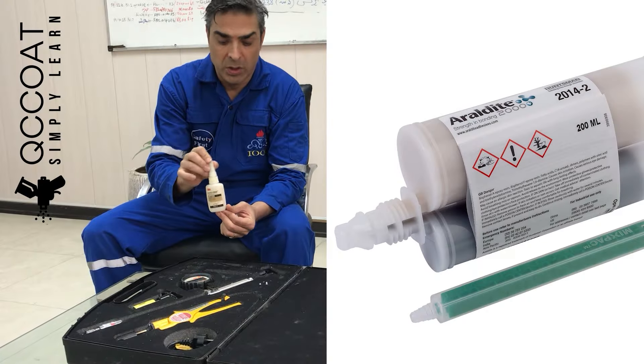If separation from the adhesive occurs and its amount is more than 20% of the surface, the test is failed. The acceptance criterion of the first condition is that the adhesion between the primer and the substrate is equal to or more than the spec or agreement. Second mode, in 10 or more tests, the separation between 20 and 60% should not be more than one tenth of the total measurements.